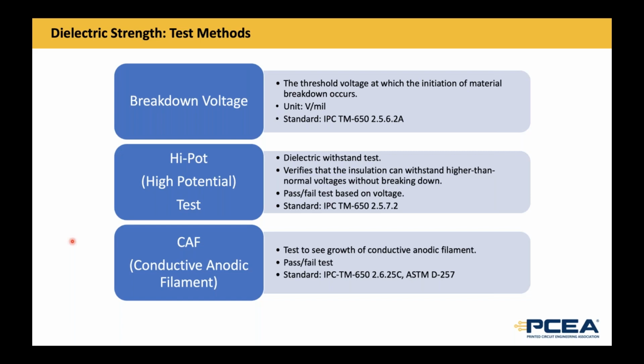Even though we tried to give some hints in the IPC specification sheets, they weren't very useful because every application required something different. High-pot testing, like Erico said, is really important when the dielectrics get very thin, because once you go down to a single ply of fabric in a dielectric, one defect can cause failure. So the cleanliness of the laminator's process is really important. But the percentage of the material used in the industry that has to pass a high-pot test is very small. Breakdown voltage, usually they're so much higher than what's required. It's not a critical variable to specify unless you are using very high voltages above typical household current.